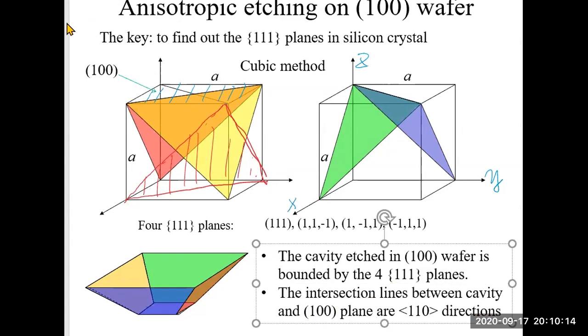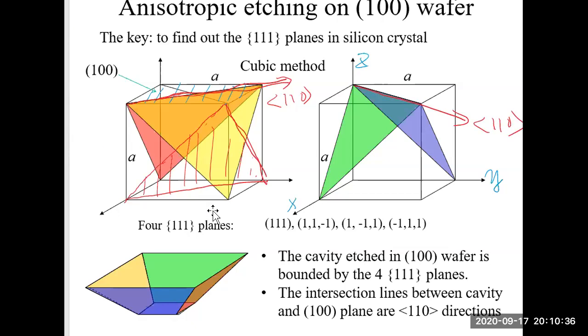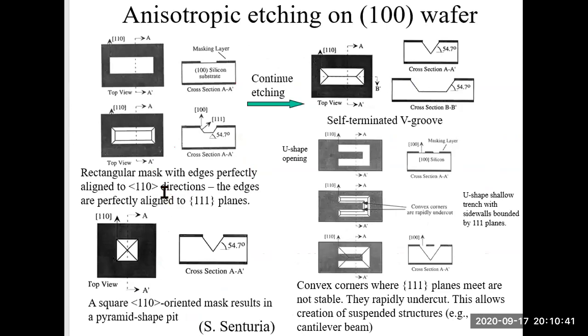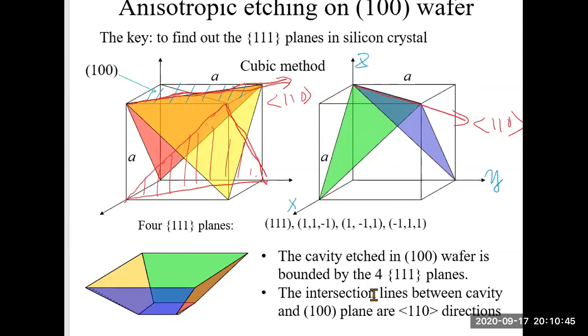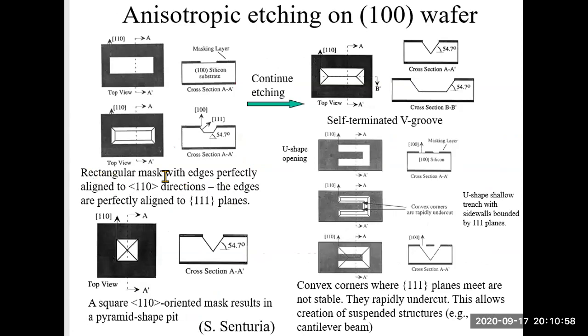Namely, the intersection lines between the 111 plane and the 100 plane, the top surface, are 110 directions. This diagonal direction is 110, and this is also 110. But if this rectangular mask has all its four edges perfectly aligned to the 110 direction, this means that the four edges are perfectly aligned to 111 planes.